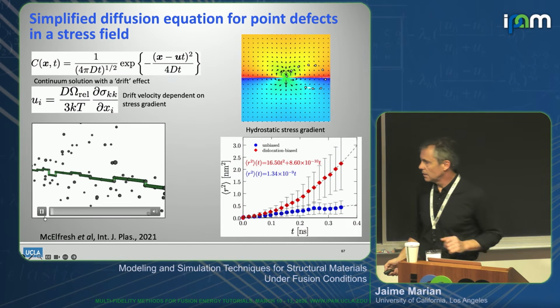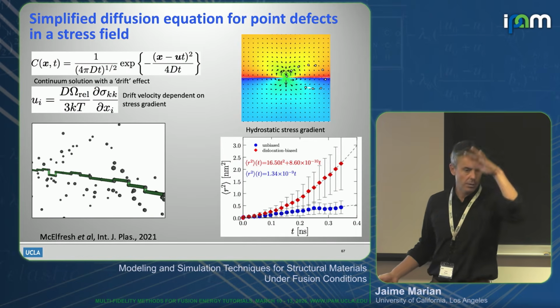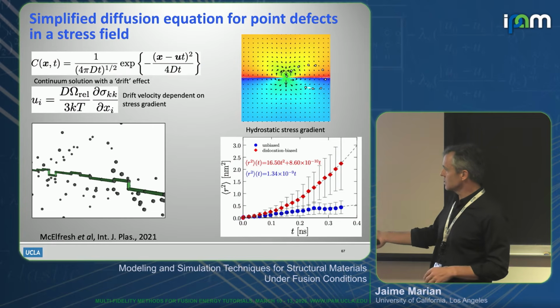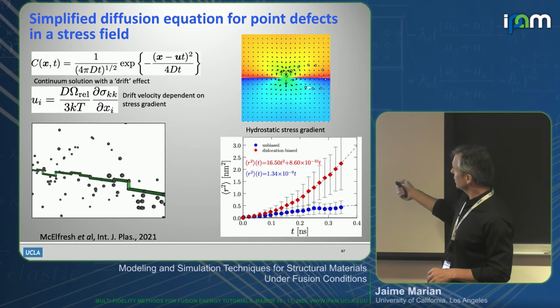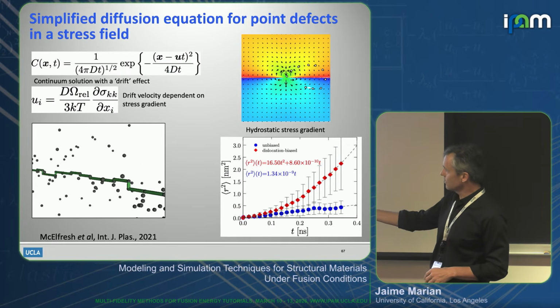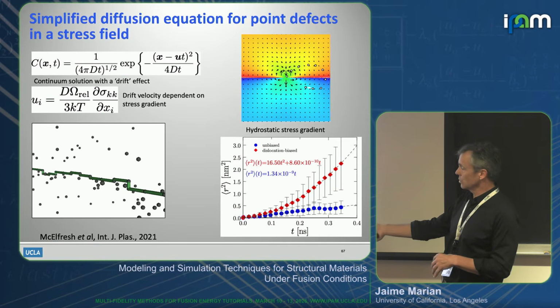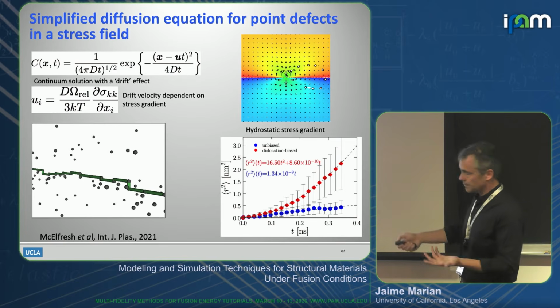Hopefully, as the loops interact, the lines start to climb. They go up, they go down. Here you see vacancies diffusing in the stress field of the dislocation, and we have to capture that through appropriate corrections to the diffusion equations. And the lines start to climb. These are lines that are discrete, so they form discrete steps.